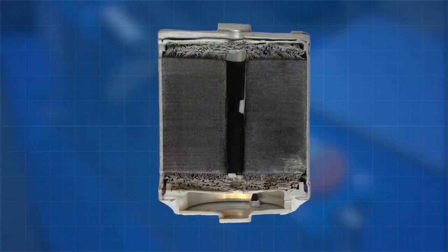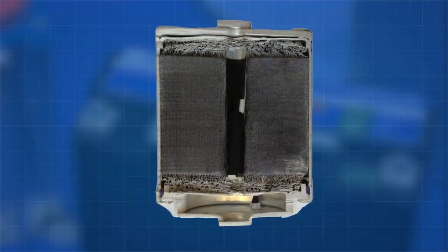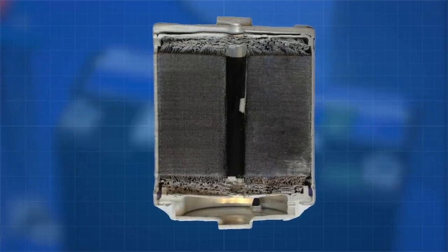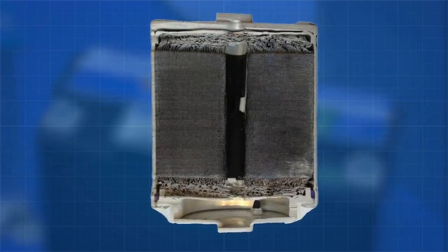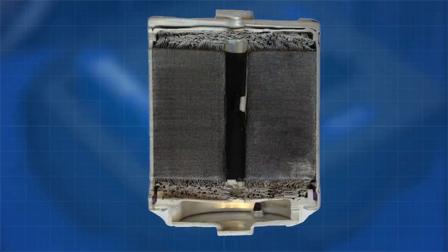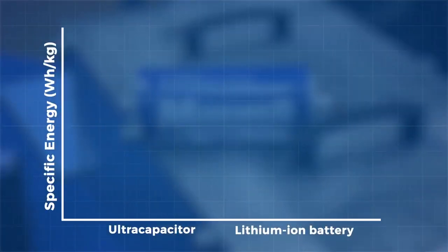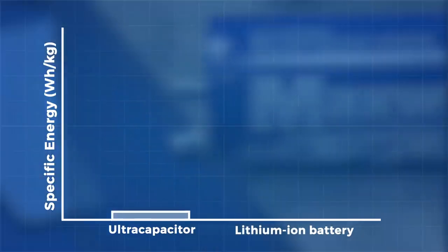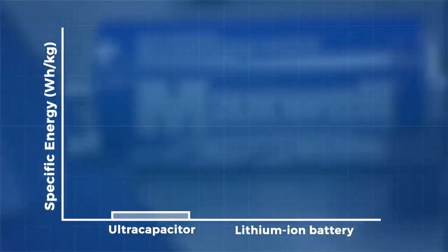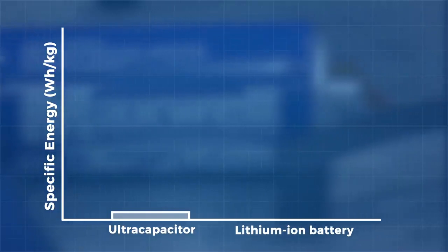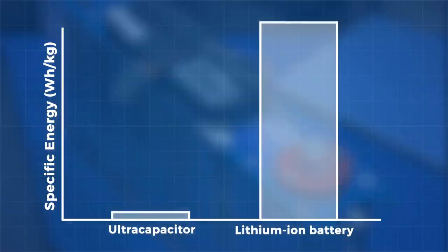This is what the inside of an ultracapacitor looks like. It contains hundreds of layers of these electrode pairs. But even with this enormous surface area, ultracapacitors simply cannot compete with batteries when it comes to energy density. Even Maxwell's best ultracapacitors have an energy density of just 7.4 watt-hours per kilogram, while the best guess for Tesla's current energy density is about 250 watt-hours per kilogram.